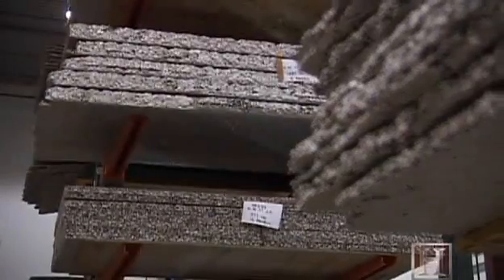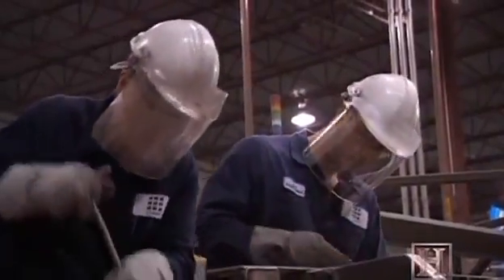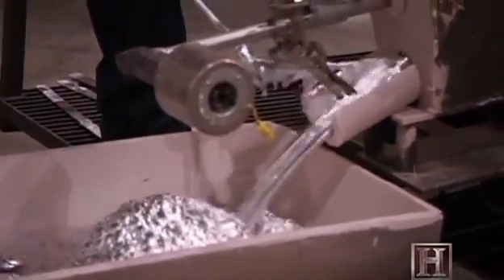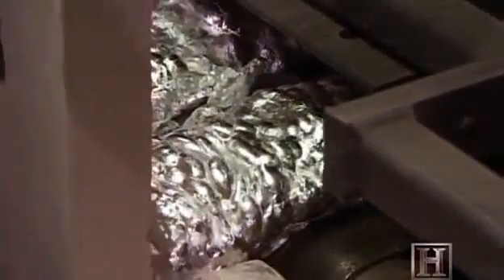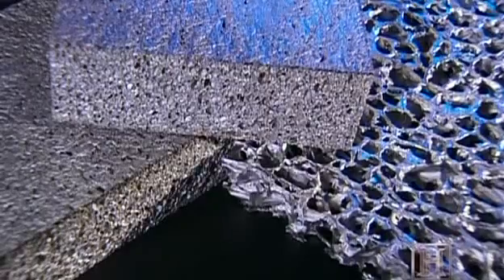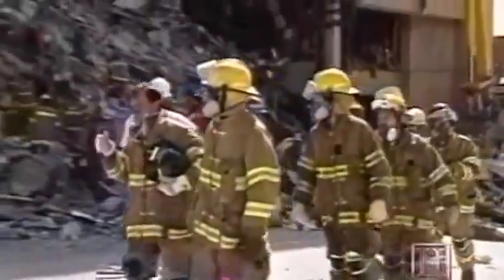But these buildings may have fared better had they been clad in an innovative form of aluminum produced by Canada's Cymat Technologies. They call it aluminum foam. Its unique sponge-like structure could prove to be a lifesaver around the globe. The foam basically absorbs the shock wave so that there isn't such a severe impact. And so if you had blast protected the concrete columns supporting the structure, there's an excellent chance that the buildings wouldn't have collapsed and a lot of lives would have been saved.